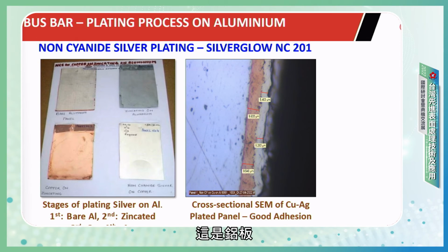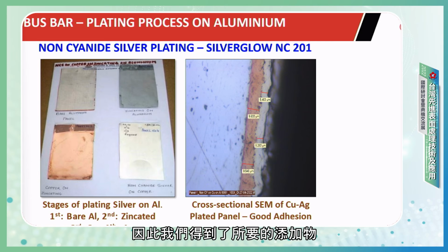This is the panels of the aluminium at different stages. You can see this is the base aluminium, this is zinc-coated aluminium, then we have the copper-coated aluminium, and then the silver. After that we have done the cross sections, and we don't see any gap between the layers, so we are getting the desired additions.